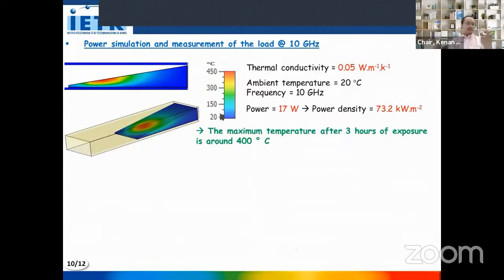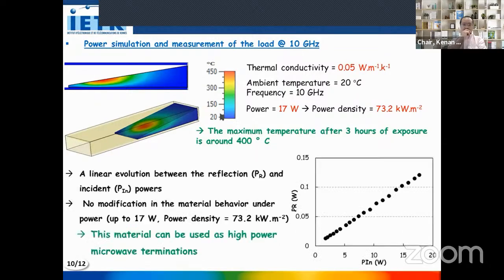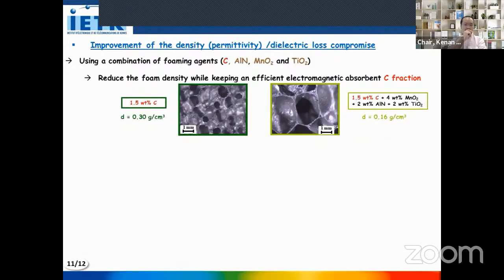The power simulation of this load shows that the maximum temperature reached under 73 kilowatt per meter square is around 400 degrees. The measurements show that for the same power density, there is no modification in the material behavior. So this material can be used as high power microwave terminations. Moreover, to improve the compromise between density and dielectric properties, a combination of foaming agents can be used in order to reduce the density while keeping electromagnetic absorption.